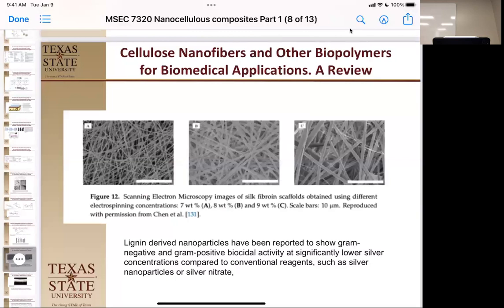Okay, so they take solutions of this, and notice that the size of the fibers changes with the concentration. If you think about it, in electrospinning you have a high voltage, you're shooting out of this cone, and so the viscosity is going to be a major component in how fast it's going to accelerate out of the cone. If it's a lower viscosity, it's going to accelerate faster than if it's a higher viscosity. That means a higher draw length, which means a narrower fiber. So we see the progression here, just 1% difference between all these. These are all the same bar size. There's a really important viscosity parameter here.